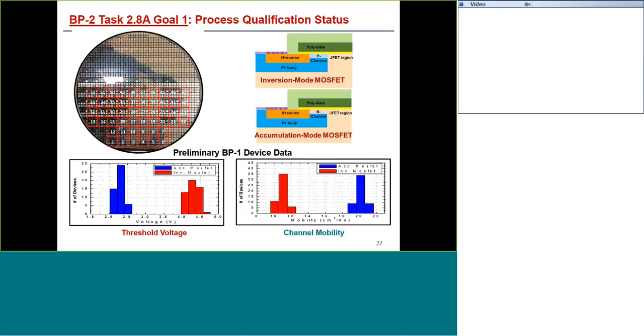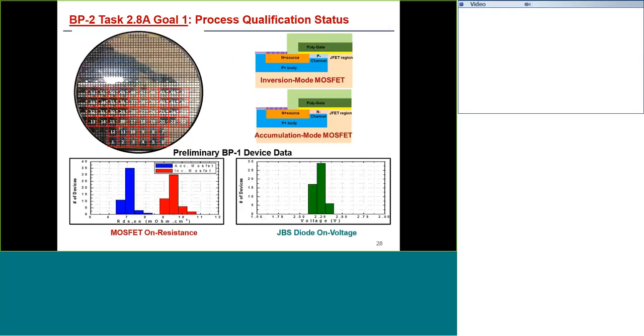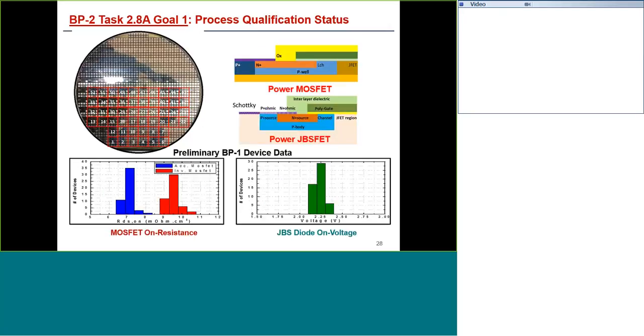So this is important in terms of reducing RDS(on). And in both cases, the mobility is very tightly distributed, which is very good from the process standpoint. We've also measured the MOSFET on resistance, as shown on the lower left-hand side. And again, we find that the distributions are fairly tight. And of course, as expected, the AccuFET has better on resistance than the inversion mode FET because of the better channel mobility.